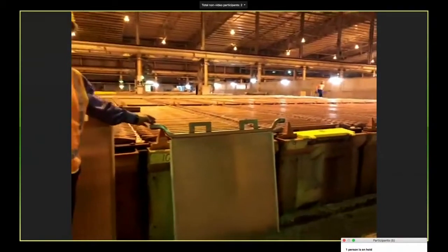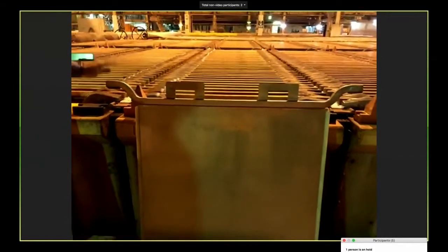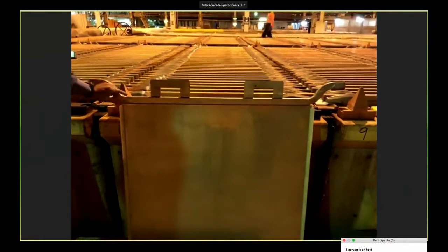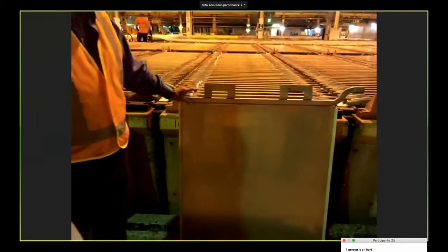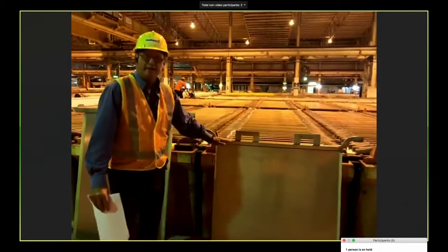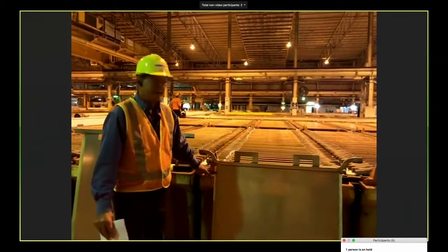The fourth plate we have here is a steer horn plate that Graham has already spoken about. Again, it is using the new ISA Kidd bar — same construction except for the steer horn shape, which offers a reduction in power costs because we have reduced the freeboard between the liquor line and the hanger bar. It is also fitted with polypropylene hinged-type edge strips.